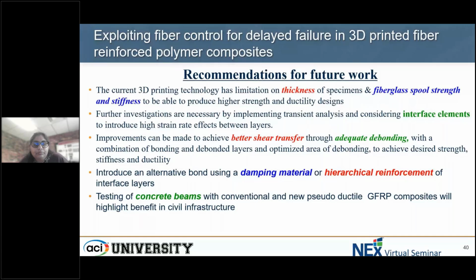For better shear transfer, but also through adequate debonding, a combination of bonded and debonded layers can also be a route that we can approach. This way, we might be able to achieve desired strengths and stiffnesses, but also that ductility that we are targeting. An alternative bond through some damping materials or hierarchical reinforcements at the interface layers can be introduced. We haven't researched that yet, but that's a great future pathway for all of you listening to think about this particular work.